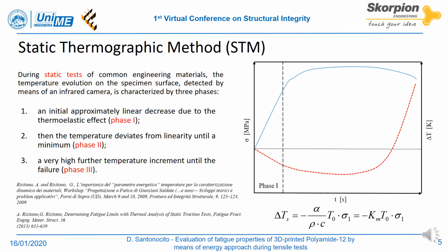An initial approximately linear decrease due to the thermoelastic effect, following Lord Kelvin's law. Then, in the second phase, the temperature deviates from linearity until a minimum, and finally it experiences a very high further increment until failure. If it is possible to estimate the stress at which the temperature trend deviates from linearity, that stress could be related to a critical macrostress which is able to produce in the material irreversible macroplasticity. This critical stress is the same stress that, if cyclically applied to the material, will increase the microplastic area up to produce microcracks, hence fatigue failure.